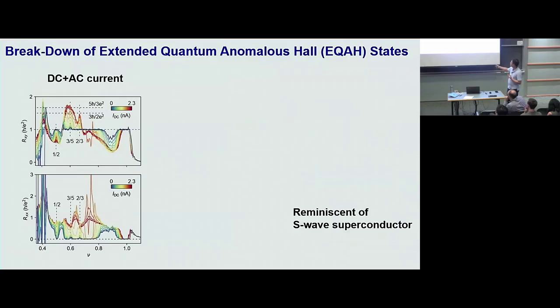Okay, if you have 0 DC current, you get basically almost the big plateau at h/e² I was trying to show you. But if you ramp up the DC current a little bit, okay, it actually gradually recovers what you see at higher temperature. Okay, the simplest explanation is current is heating it up, so it's effectively 300 millikelvin electronic temperature. However, there's some non-monotonic thing going on. As you can see here, from blue, which is the lowest current, to red, which is the highest current, in the middle, there are some big jumps, okay, in the Rxx.